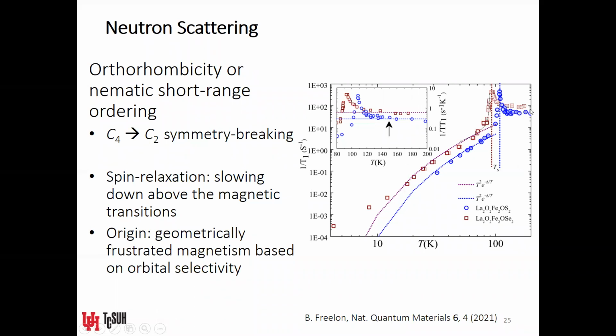As you go farther and farther into high temperature, but as you approach the Néel temperature, which are these dashed vertical lines, the spin relaxation rate increases quite a bit, overall indicating that there's a critical slowing down as you go higher and higher in temperature away from the magnetic phase transition. That's indicative of nematic fluctuations.